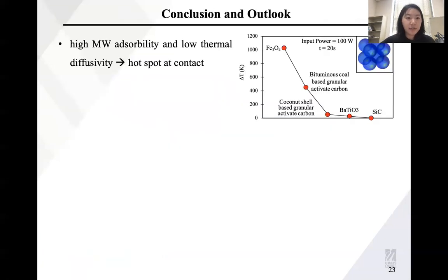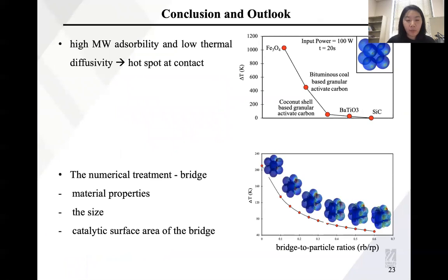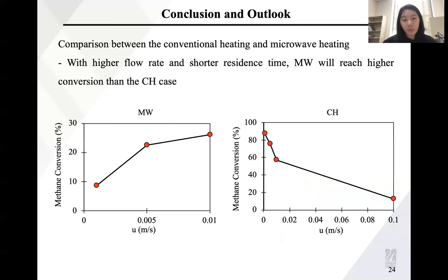Going to the conclusion, we know the main factors leading to hot spot formation are the microwave absorbability as well as the thermal diffusivity. And we know that we need a better way to numerically treat the bridge. For example, how to tune the material of the bridge, how to tune the size of the bridge, and how we treat the catalytic surface area of the bridge so that we can keep the same temperature profile and the same kinetics as we use bridge treatment for the touching particles. And we also have the preliminary conclusion that with higher flow rate and shorter residence time, the microwave can reach higher conversion than the conventional heating case.